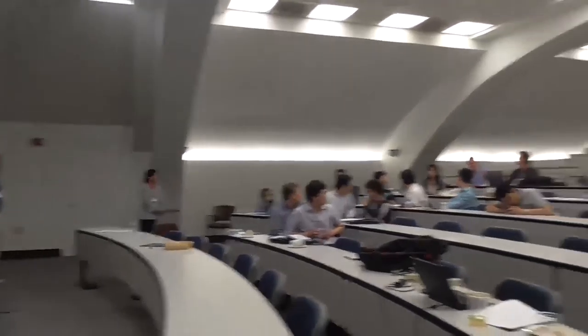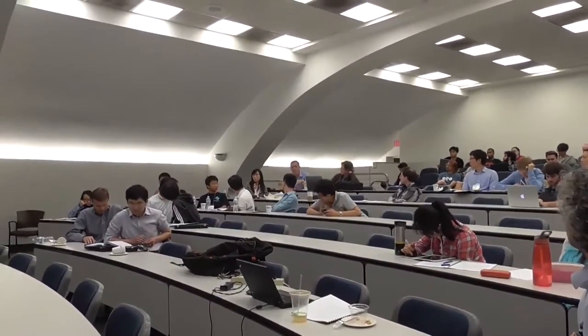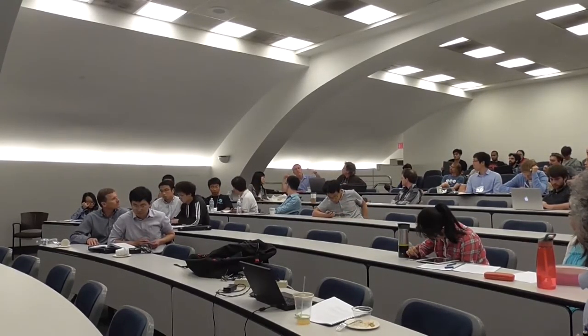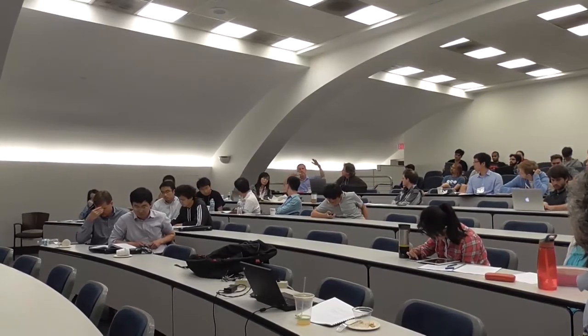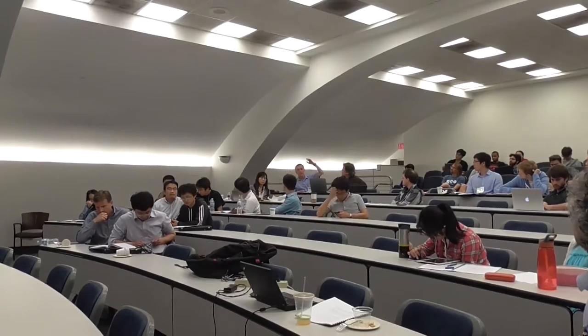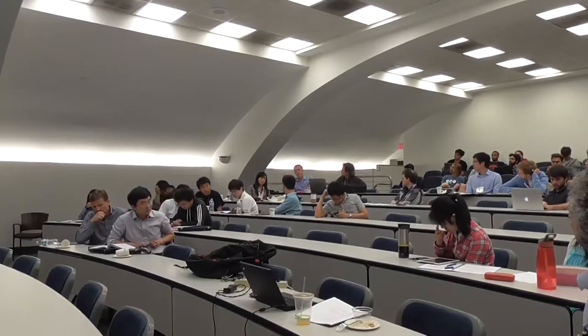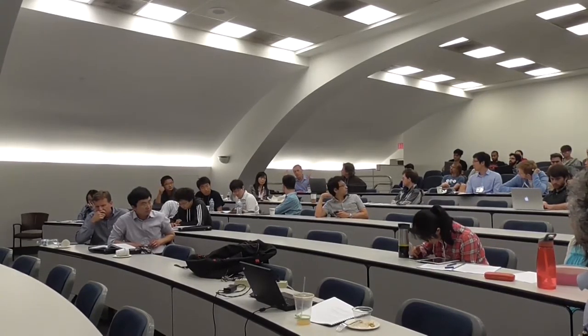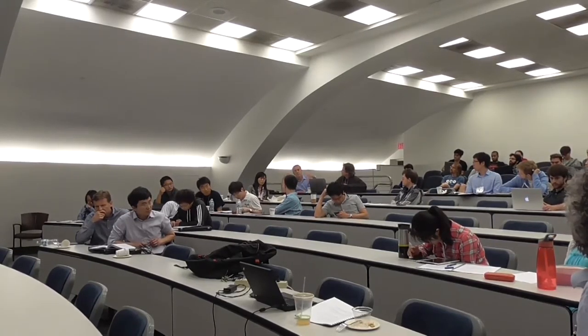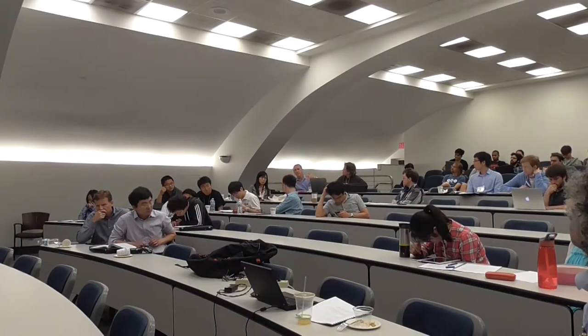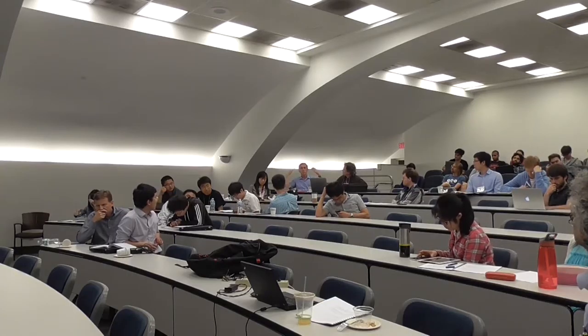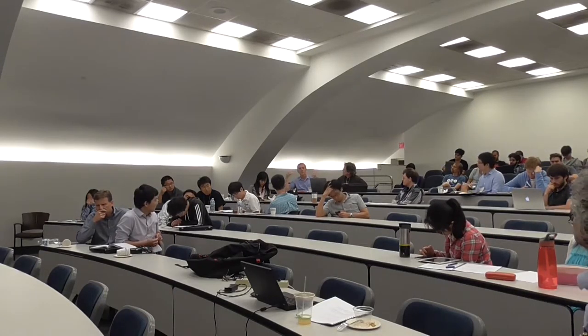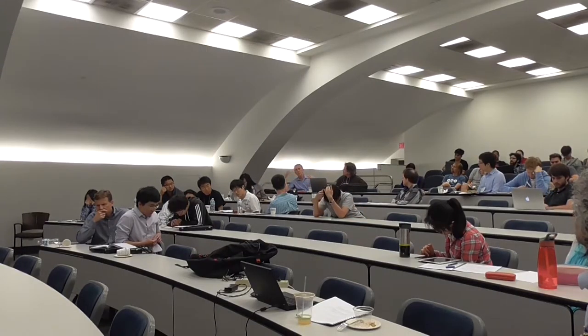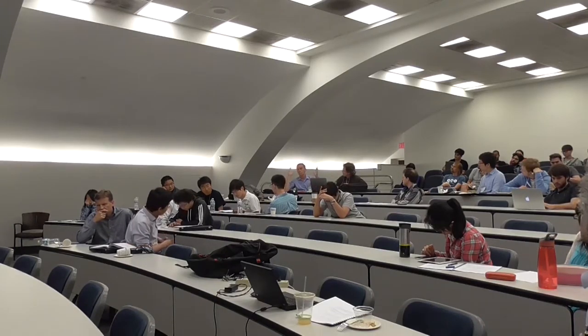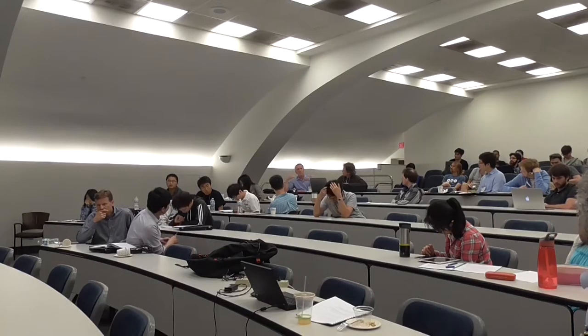Yeah. Can I come back to the experiment? Because as we know, samarium hexaboride was first investigated more than 50 years ago. The general understanding was that there is an in-gap state, some 3 to 4 millielectronvolts from the bottom of the conduction band. But all the up-to-date, modern spectroscopic methods like ARPES, photon spectroscopy, somehow do not see these in-gap states, even when the samples are not clean, for instance when there are donor states coming from imperfections or impurities. I do not understand it, because many of the microscopic phenomena that are investigated, transport, specific heat, and so on, have somehow seen these in-gap states indirectly, but these new methods do not see them at all.